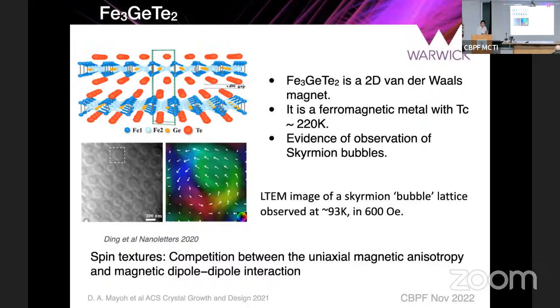This is a centrosymmetric space group. So you might ask, why? How is the skyrmion lattice stabilized here without the all-important Dzyaloshinskii-Moriya interaction that I said was important? Okay, so that's still not very well understood.